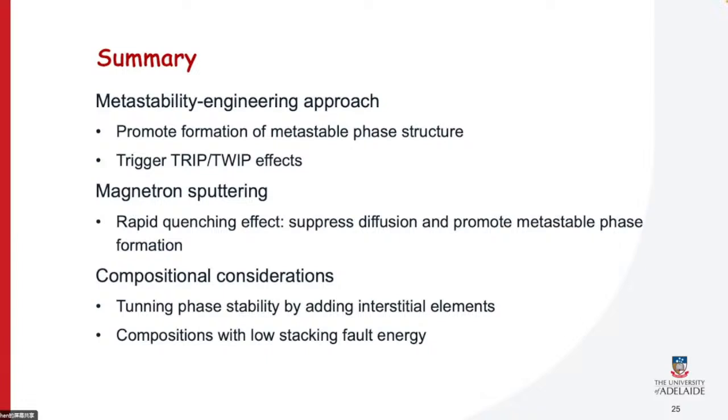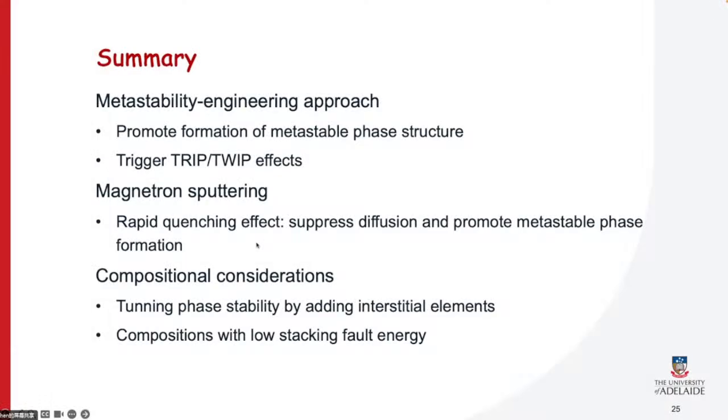To sum up, in this talk we mainly focus on the metastability engineering approach. So what we do is we promote the formation of metastable phase structures, such as the FCC and HCP dual phase structure. And we want to trigger the phase transformation and the deformation twinning. Because the rapid quenching effect can suppress the diffusion and promote the metastable phase formation.